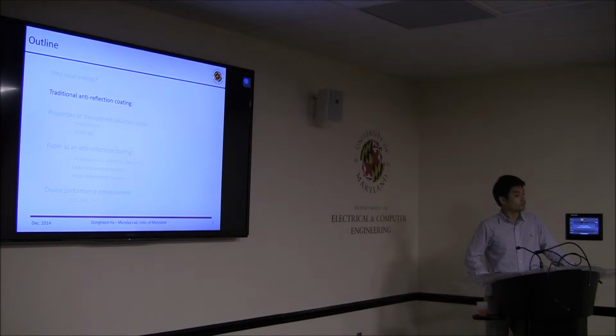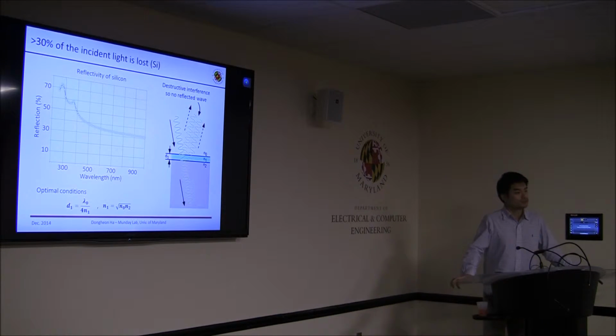So, okay, we are going to use solar energy. And to boost the efficiencies, people have used thin film-based anti-reflection layers. I'm going to talk about the traditional method for that. Due to the nature of optics, we cannot avoid more than 30% of light loss at the interface between air and our solar cells. For instance, the left figure shows the reflectivity of silicon, which is one of the most popular materials for photovoltaics. And we know that throughout the whole spectrum, the reflectance is even greater than 30%. So we're going to reduce this amount.